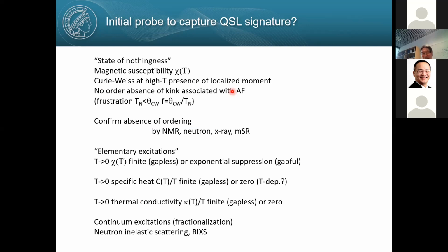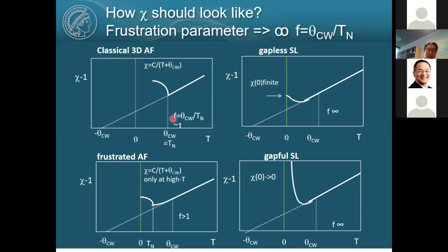Once you make a material with triangular lattice, you first measure magnetic susceptibility. You see Curie-Weiss behavior at high temperature, confirming a local moment there, and from the Curie-Weiss temperature you get the scale of interaction. This is a cartoon picture: if you plot 1 over chi as a function of T, Curie-Weiss behavior gives a straight line, and the intercept temperature is the Curie-Weiss temperature. Negative means antiferromagnetic, and in a classical antiferromagnet, magnetic ordering takes place around the Curie-Weiss temperature, the mean-field transition temperature.